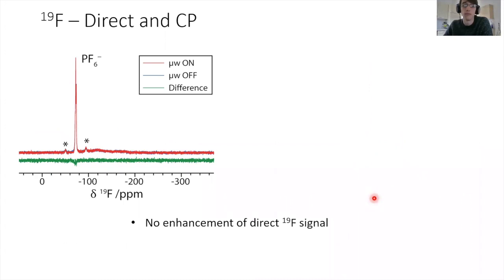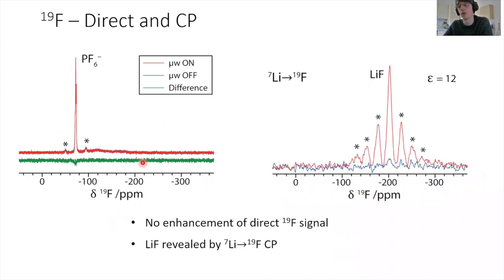Finally, we looked at fluorine. So in the direct fluorine spectrum, you see the PF6 anion that comes from the electrolyte. That's not in the SEI. The SEI is impermeable to PF6, and so it's not enhanced. We see nothing in the difference spectrum. However, if we do lithium to fluorine cross-polarization, we can now reveal lithium fluoride, pretty low concentrations of lithium fluoride. But importantly, we get a very large enhancement compared to the enhancement of other lithium species. And that tells us that this lithium fluoride is right at the surface of the lithium metal. And that's something that had previously been proposed, but it's quite difficult to prove.